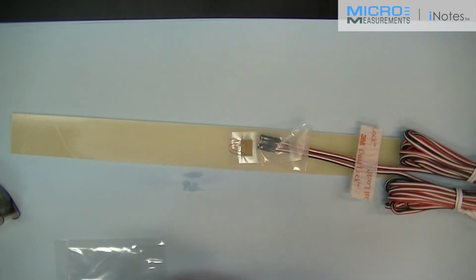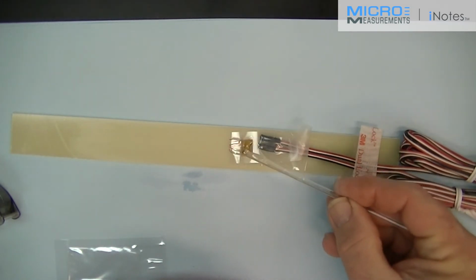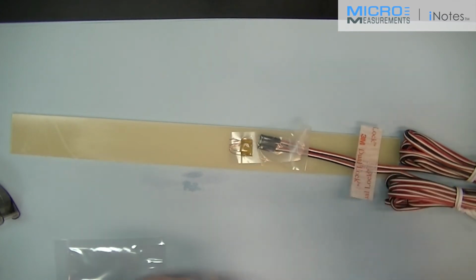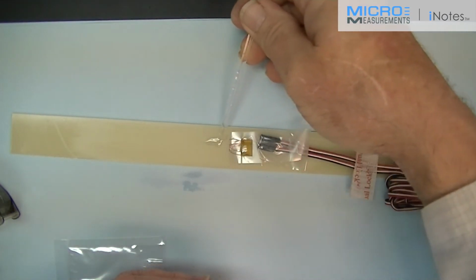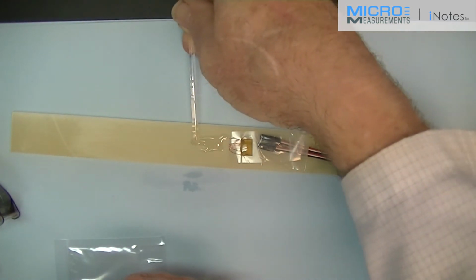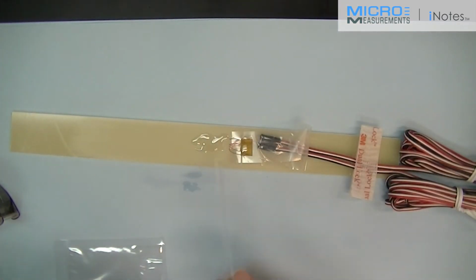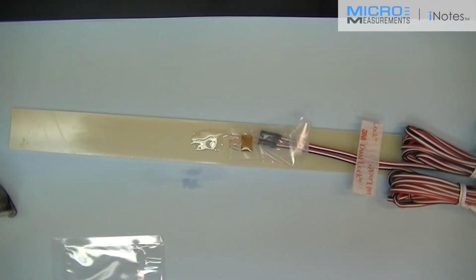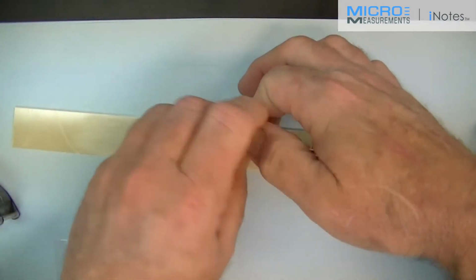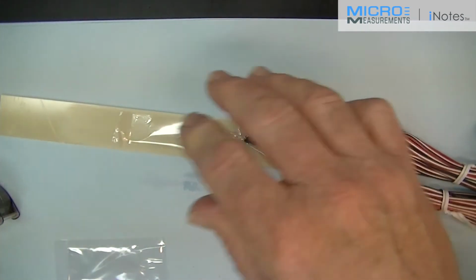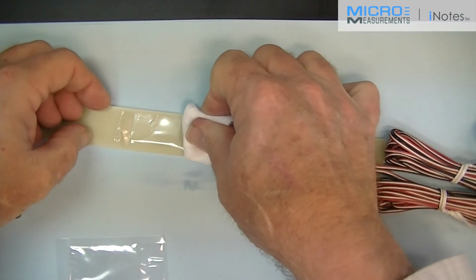The previously mixed AE10 will now be applied, both to the backing of the gauge and to the surface of the part. We're going to make sure both are thoroughly wetted so that you'll be sure and have a good bond. Be sure to cover a significant area, maybe bigger than you think, so that you have both surfaces wetted. Make sure you cover a big enough area on the part. I'm then going to reposition the gauge using a gauze sponge folded into quarters to squeegee out the excess adhesive.